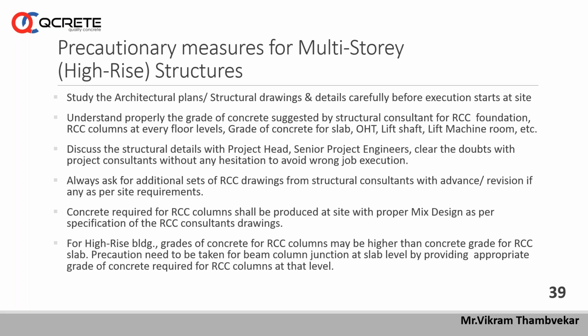So while making fresh concrete at site, for casting of concrete, care should be taken that the proper grade of concrete is being produced with the proper mix design. Many times what happens, people take a mix design once and they follow it for a number of years and they say, "Arey, we have the old design." That is not a good practice. Whenever there is a new material procured at site, it is a standard practice to get it analyzed properly and get the mix design revised, or get a new mix design. And of course, with that mix design, again have some batch trial with a lesser quantity, cast the cube, see the quality of concrete, see the workability, check the use of your admixture, and then only follow it.